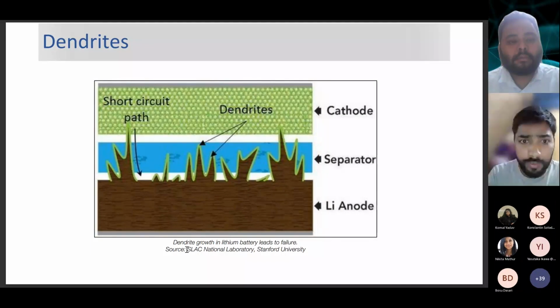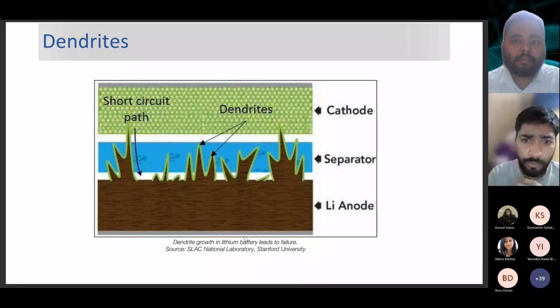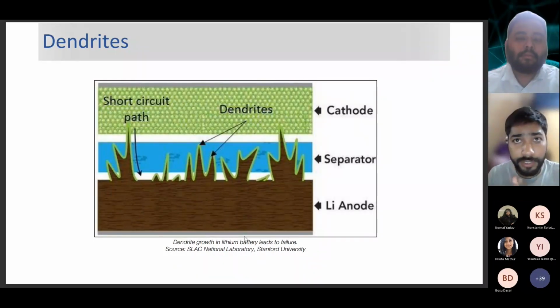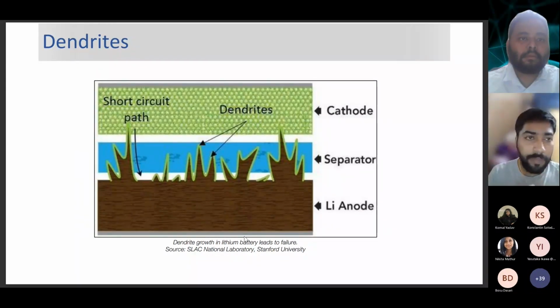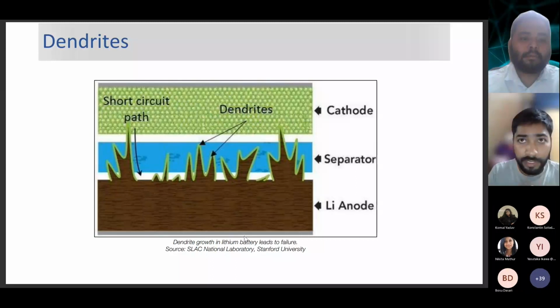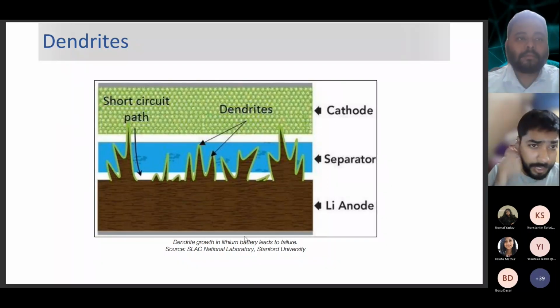So this is one of the major challenges we have when we try to look into new forms of anodes which have higher energy densities, because pure lithium metal anodes or silicon based anodes have the capacity to expand rapidly, and when we use them with the current liquid electrolytes, they are not able to suppress this dendrite formation. And if this dendrite formation is not stopped, it's really a difficult challenge to replace the existing anodes with a pure lithium anode, or with a silicon based anode, or any other high energy dense anode. Next slide.